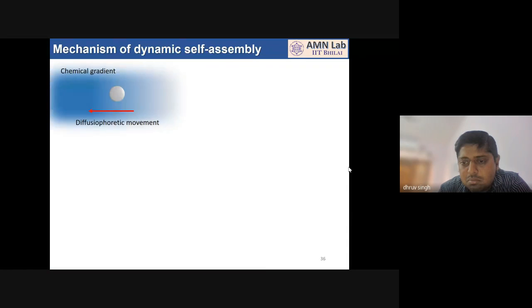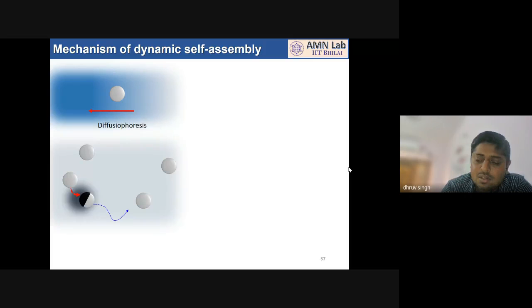If I go to the mechanism part, this whole reversible assembly is governed by a very simple principle: if you put a colloid or a particle, you don't need a Janus particle, you just put a particle in a chemical gradient. Then, following diffusophoretic movement, diffusophoresis, the particle will start to move towards the higher chemical gradient or lower chemical gradient depending on its surface properties, but it will move. So in this case, our active particles are forming a local chemical gradient. I discussed this thing. Following this chemical gradient, the surrounding particles may come in and get attached. And further, because everything is moving, this movement will facilitate the collection of more surrounding particles, and the whole structure will grow in size and form a crystallite.